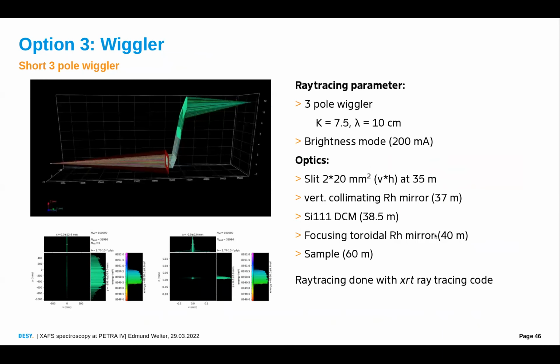And the third option would then be a wiggler. I did some ray tracing using XRT from Konstantin with a 3-pole wiggler with a really moderate K. So it's not a real, hard wiggler. It's somewhere between an undulator and a wiggler, kind of an undulator, with a K of 7.5, and that would deliver about 10^12 photons in the monochromatic beam at the sample position. But this calculation was done without any filters and without considering that the optics might not be ideal, etc.